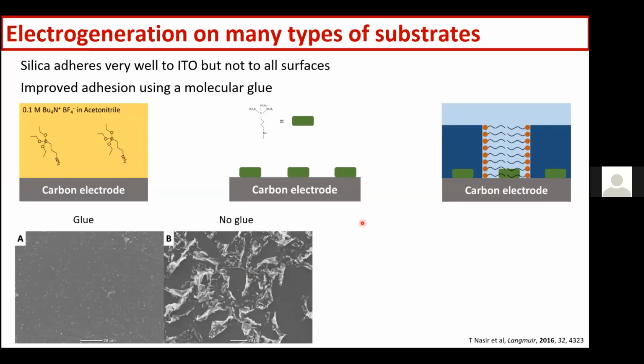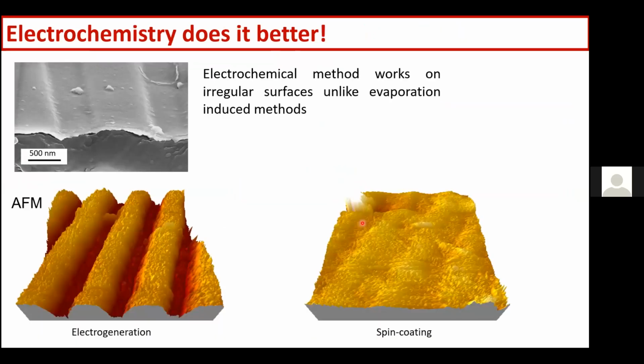And one of the good things of the electrochemistry is that it allows us to control the thickness of the film because it's linked to the amount of charge that is passing through the electrode. And if you have a rough surface, so here you have a rough surface with hills and valleys, you can see that with electrogeneration you can follow the roughness of the film. But if you do this with spin coating or another evaporation induced method for the sol gel process, then you will completely fill the gaps, and you would lose the structure of your electrode.